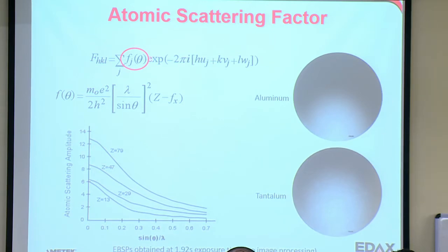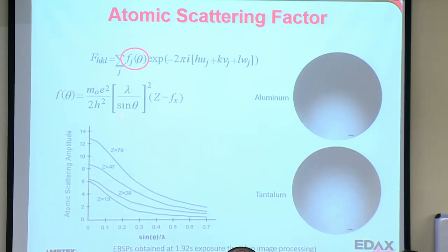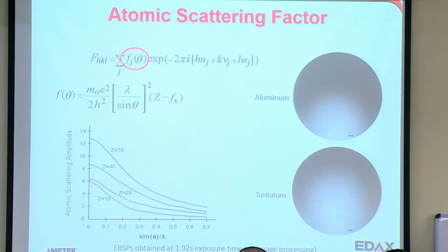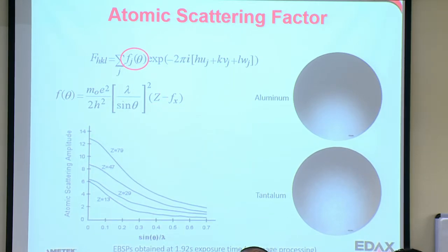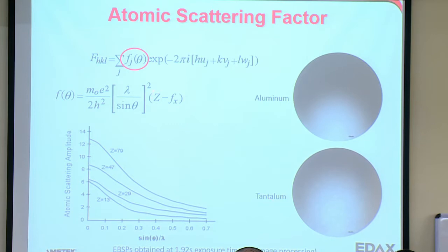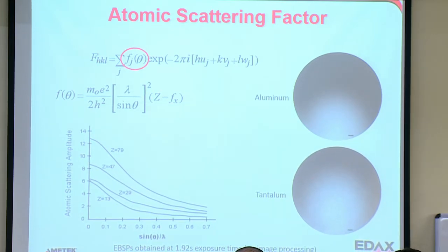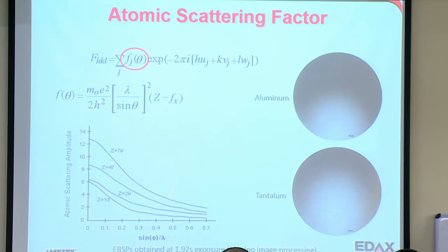The important factor here is the atomic scattering factor. It's a function of this big equation. The key thing I want you to note here is Z, the atomic number. So if I do a diffraction pattern for aluminum, it looks like this. The EBSD pattern for tantalum looks like this. This is at the exact same conditions. You can see in the tantalum, which has a high Z, you see a lot more bands, there's a lot more intensity. It's a little easier to get diffraction patterns from heavy materials than it is from the materials higher up on the periodic table.